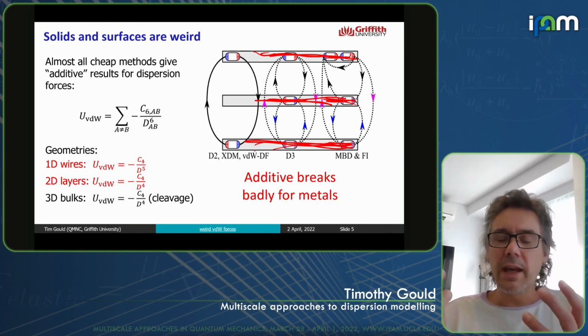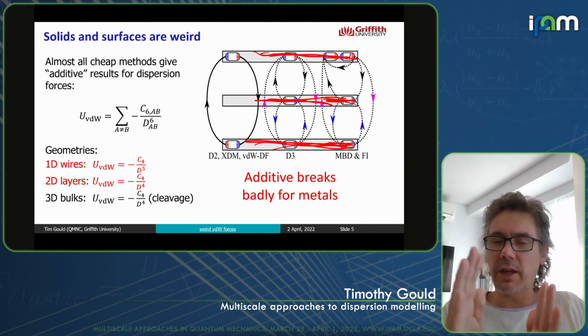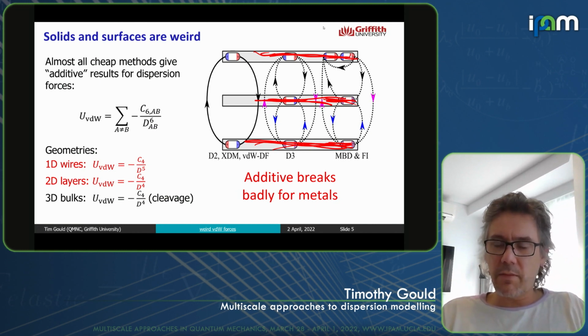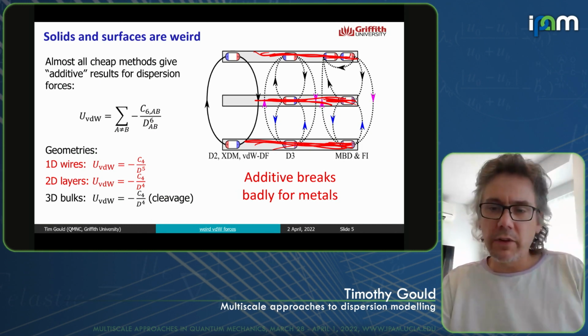So what we can actually do is get coupling between layers or wires at longer scales, which look like extended, they're not just a single atomic thing. They are a collective polarizability mode within the layers. And it turns out that if you've got a metal, then these collective modes are so strongly coupled, and this is not surprising because a metal has 0 band gap, it has good conductivity. Basically, electrons can move a long way at fairly low cost.